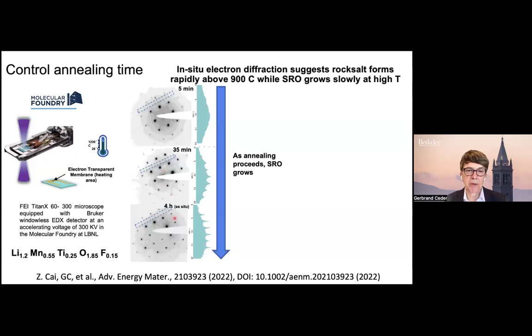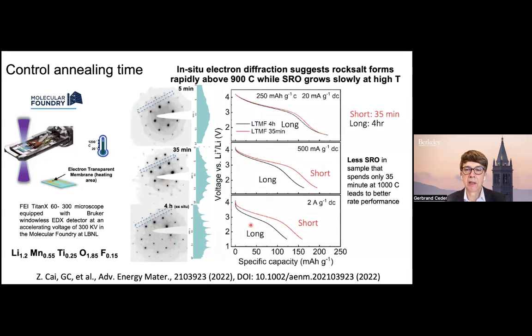And then as you let the material sit, it actually tends to form short-range order. So the lesson here is that in the synthesis, the rock salt forms very early, but the short-range order forms only with time. And you see that in the performance. If you look at the performance